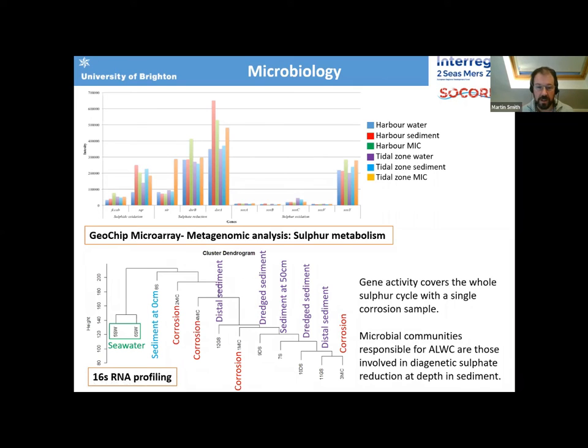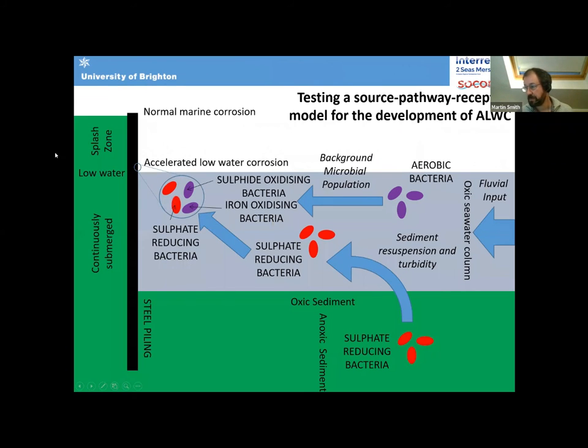So in terms of our original idea of the causative mechanism, we can be fairly confident now that the sulfate-reducing bacteria that are responsible for the accelerated low-water corrosion are coming from sulfate-reducing bacteria populations in the bed sediment that are resuspended by dredging, by ship movement, colonizing steel surfaces, and then we've got these blisters forming where the outer surfaces are colonized by sulfide oxidizing bacteria. They're generating the green rusts, the iron sulfates, and against the steel surface where we've got local anoxic conditions, we've got sulfate reducing bacteria generating hydrogen sulfide against the steel surface.